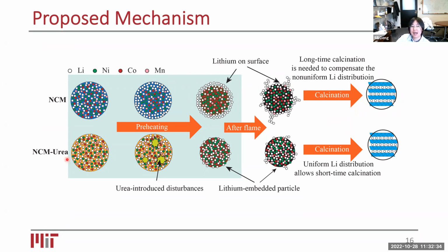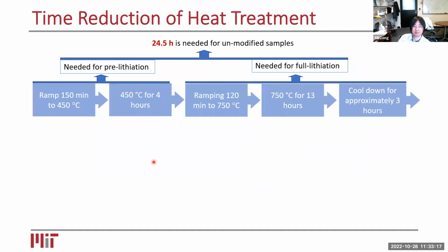metal oxide. Whereas when we add urea to the precursor, urea itself is sensitive to temperature. It generates bubbles, which introduces internal motion inside this droplet to enhance mixing. So you could imagine there are bubbles that act as stirrers, trying to enhance the mixing such that we can get uniform distribution for all 4 elements inside this. That is the foundation for the short calcination time needed for the annealing process.